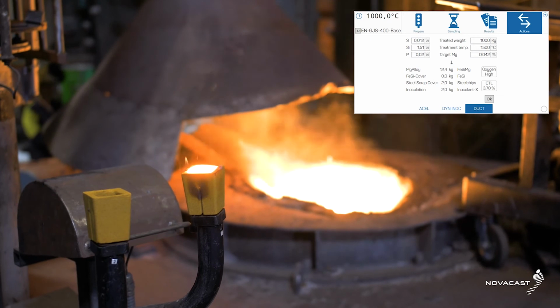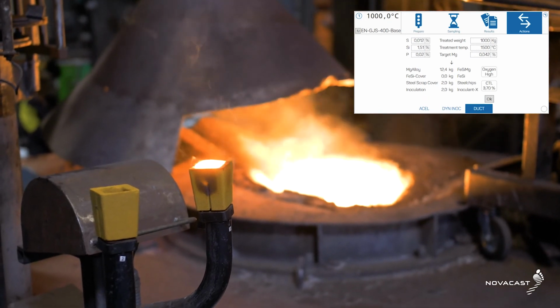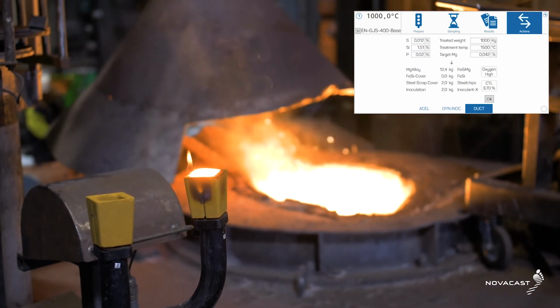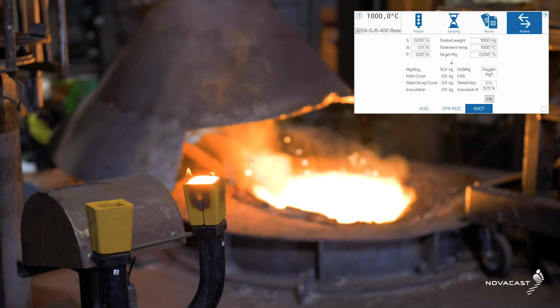At the same time, when we are talking about ductile iron production, ATAS also uses spectrometer information such as sulfur, silicon, phosphorus, and target weight, treatment temperature, to give you an exact magnesium content calculation, as well as steel scrap cover and inoculant addition. So this is extremely important. Usually sulfur, silicon, and phosphorus are grabbed automatically from the spectrometer.